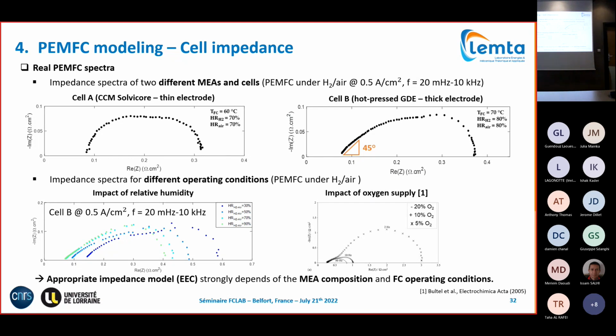Whereas if you have thick electrodes, which we can see with self-assembled homemade MEAs, hot pressed using gas diffusion electrodes pressed on a membrane, it is for sure less perfect than commercially available MEAs. Here we have a spectrum characterized by a 45-degree slope at the highest frequency, a volumetric character, just remember the slide before. And our spectrum will also depend on the operating conditions. For example, with different relative humidity, meaning humidification of your polymer membrane, which needs water to correctly transport positive ions from the anode to the cathode.